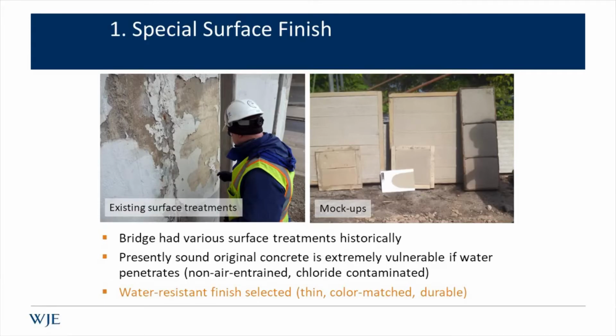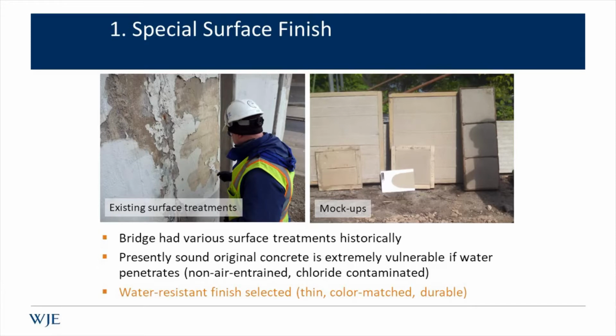And the first was this idea of keeping water out of the concrete. Generally for historic structures, film-forming coatings are not well received or not an option. This particular structure had a number of coatings that had been applied over the years, and so through discussions with the historians, and obviously given the risk that if you don't coat it, you're going to lose historic fabric, there was a discussion and decision ultimately made to select a special surface finish that was thin enough so that we would still see the board form finish, which was one of the historic features. That color matched the original buff concrete, would be durable and high performing, and most importantly would protect that original concrete that is not air entrained and generally had very high chloride levels.